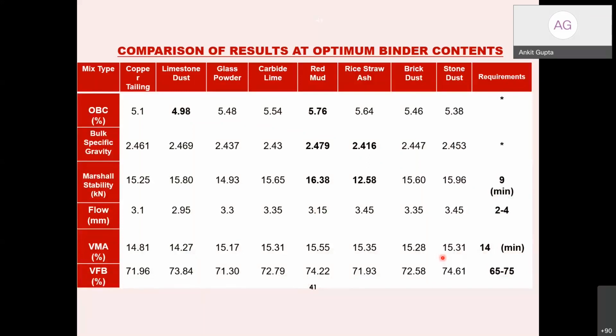Now you will see that as compared to the stone dust, because this is our comparative value, the limestone dust is even using a lower amount of bitumen content. The OBC is lower than 5.38, that is 4.98. So we are saving bitumen, and bitumen is the costliest part in our whole pavement materials. If we are saving bitumen, then obviously we will save a lot of cost. So limestone dust is only requiring 5% as compared to 5.38 for the conventional stone dust.